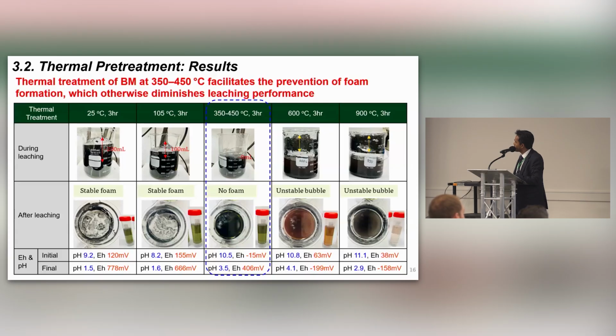But at 350 to 450 degrees, when we apply that type of thermal treatment, we observe that we can avoid this kind of stable foam formation. And at very high temperature, we observe some unstable bubbles. Actually, we assume that's because of carbon dioxide emission. So our hypothesis is that during this temperature range, we could eliminate the binders and organics. That is the reason for avoiding this kind of formation.